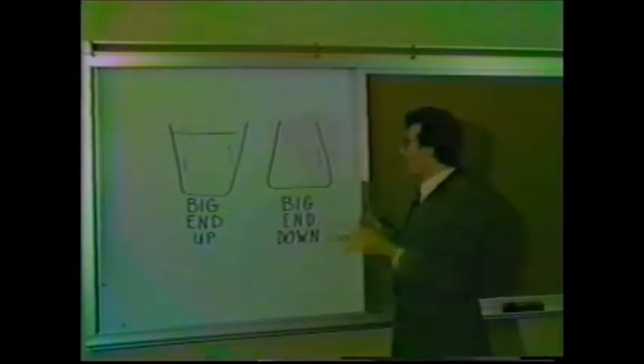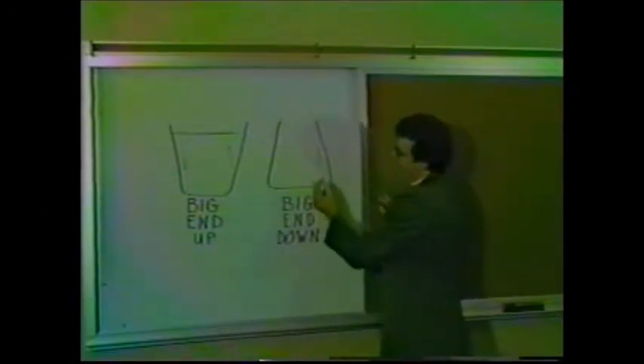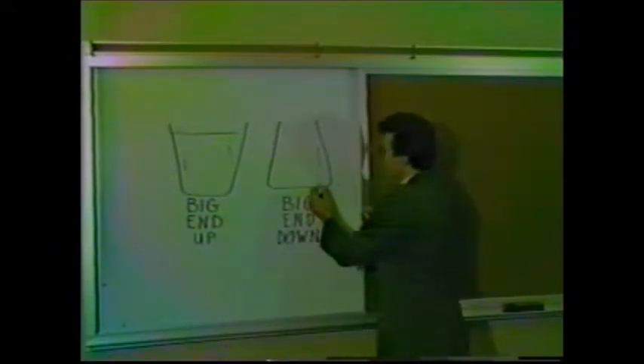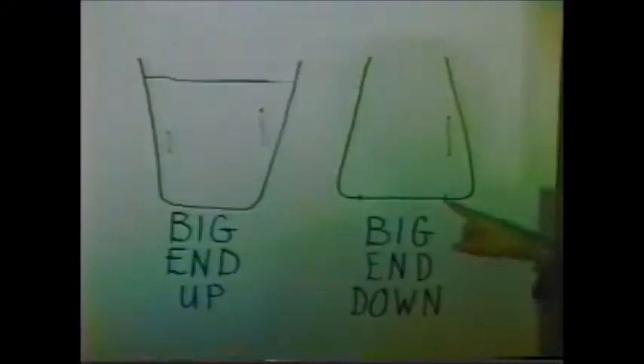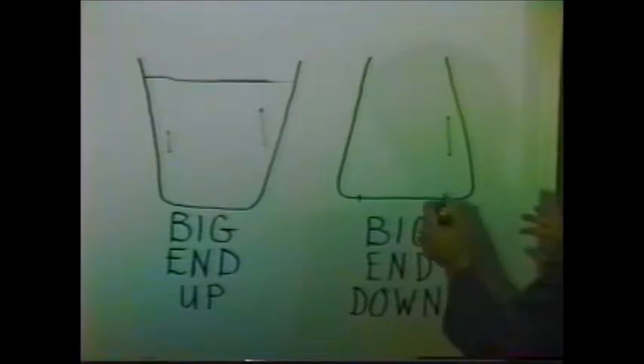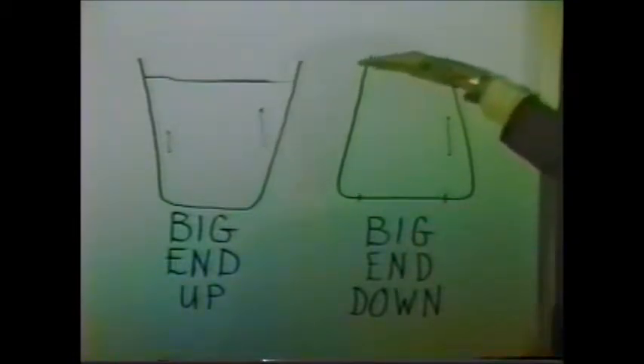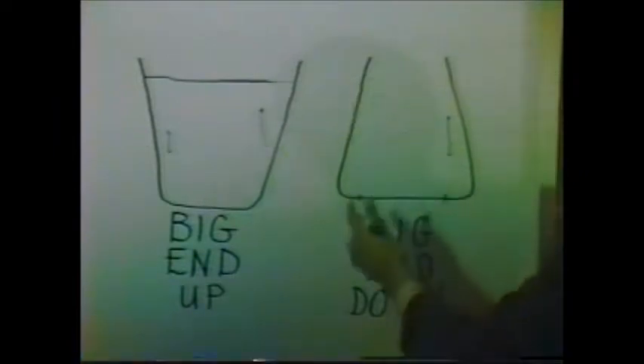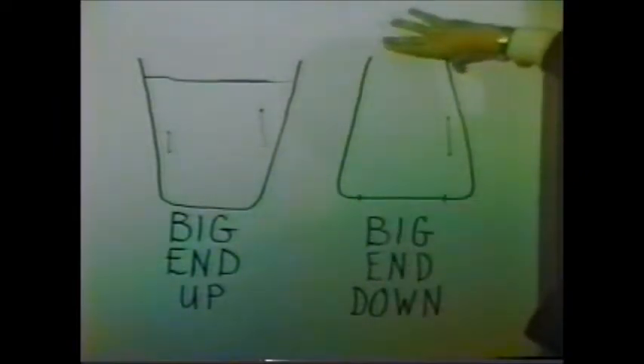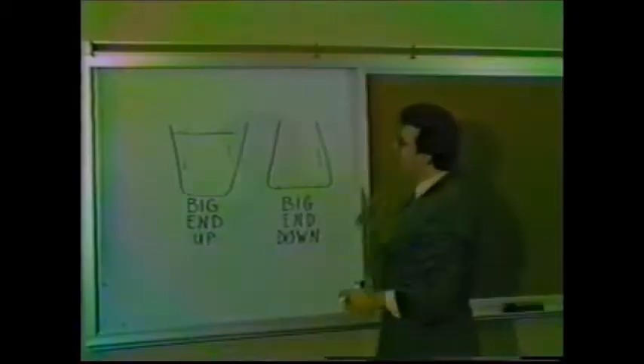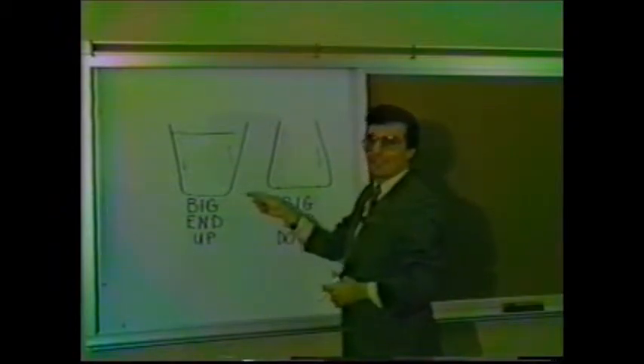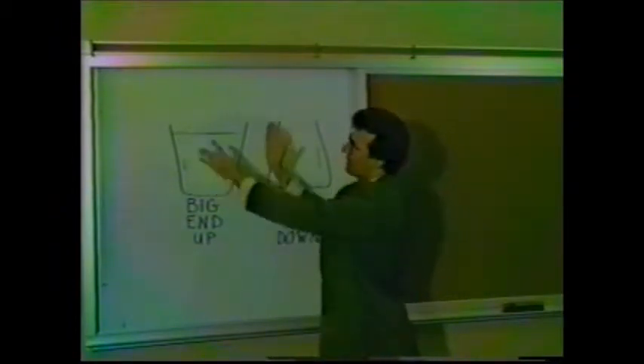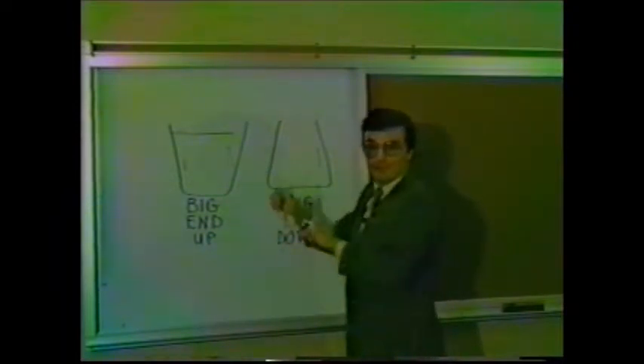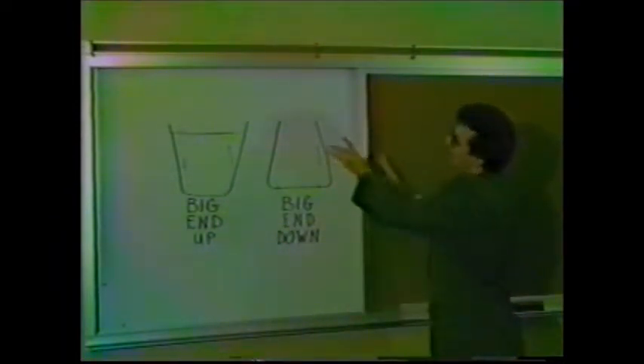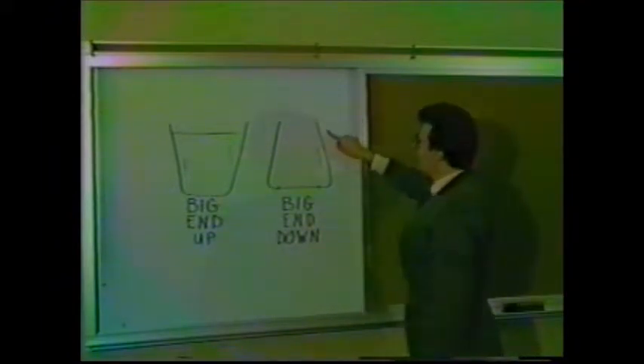Now, at first it doesn't sound right, because how would you get the steel out? But the big end down ingot mold is actually a two-piece mold. The bottom of the ingot is called a stool. They'll cast the steel and allow it to solidify. Once the steel has solidified, they can grab the top of the mold itself with a crane and just strip the mold right off the top. Contrast that with a big end up mold. To get the steel out of it, they have to turn the mold on its side and knock it out from the bottom. So there is less cost associated with getting the steel out of a big end down mold.